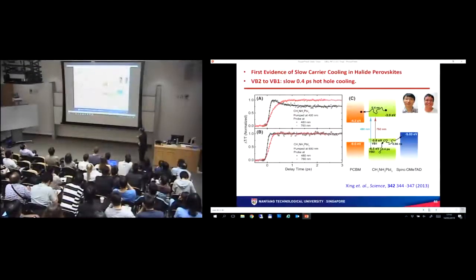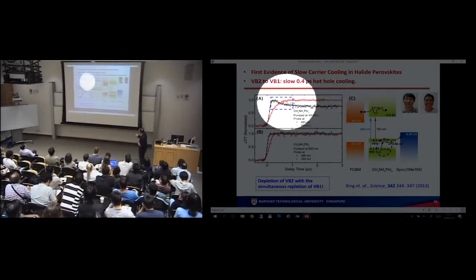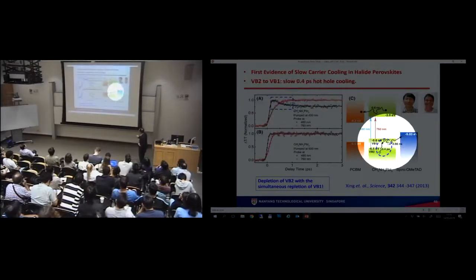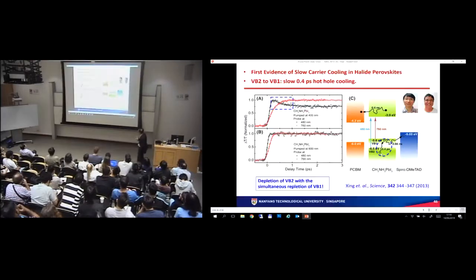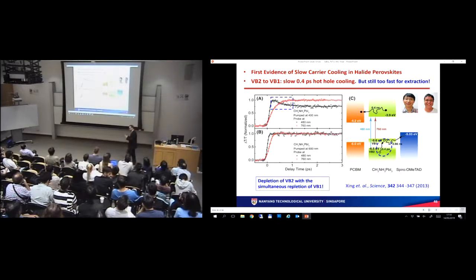Just a recap, the first evidence comes from these interacting levels that we see, the 0.4 picosecond hot hole cooling, where we see a depletion of one level followed by a simultaneous rise in the signal, the filling of a second level. Now, we see a slow hot hole cooling process of 0.4 picoseconds, but that is actually still too fast to make any practical device out of it.